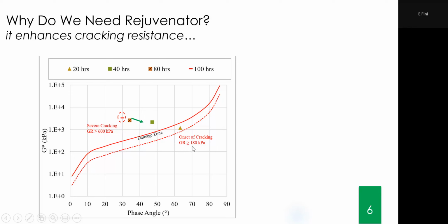If it's below the dash line, then it's safe. And as it gets higher and higher, upward, it becomes more prone to cracks. So when we want to improve it, we want to make sure it doesn't crack. Literally, if the sample is up here and it cracks, and your rejuvenator doesn't move it downward, then you haven't really improved the crack. You may reduce the modulus a bit, but if it's still too high, it could still crack.